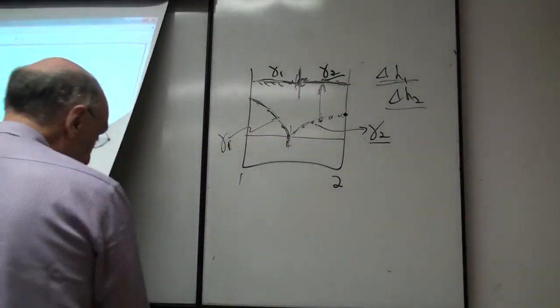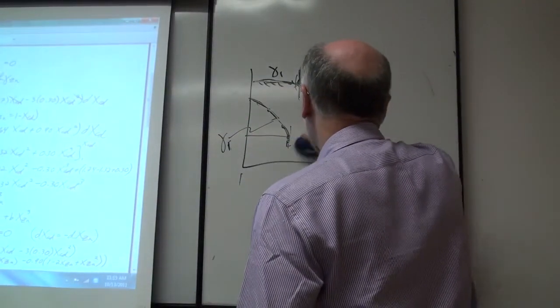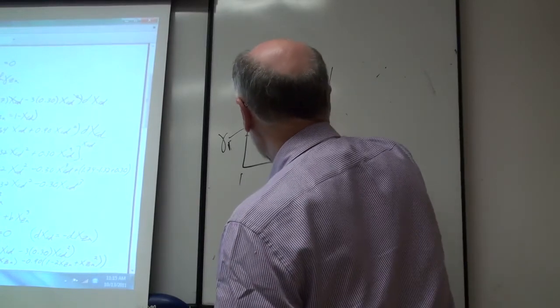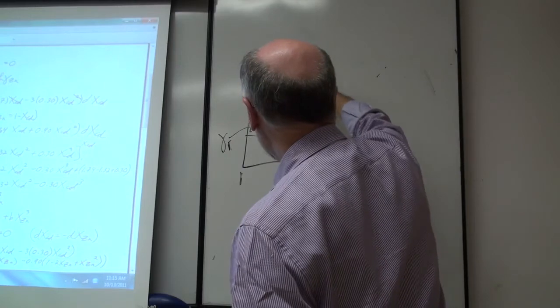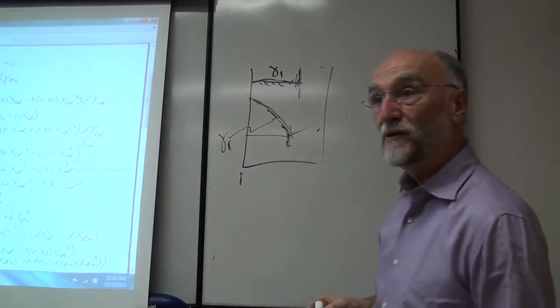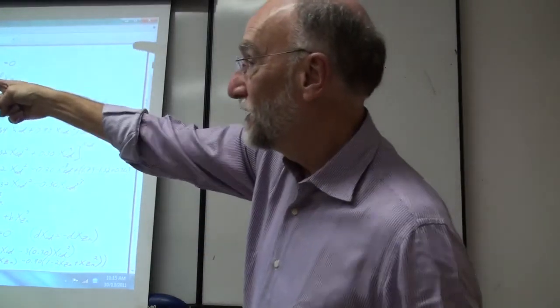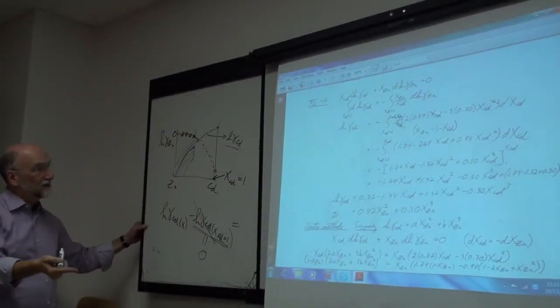But in many cases, when you're fitting up phase diagrams, more often than not, you probably don't have too much over here. You do have a liquidus over here for component 1. So your liquidus for component 1 gives you gamma 1 over that region. Now you're doing the same thing as I did over here. You're getting gamma zinc over this region, fitting it up to an expression, and that expression gives you log gamma cadmium.